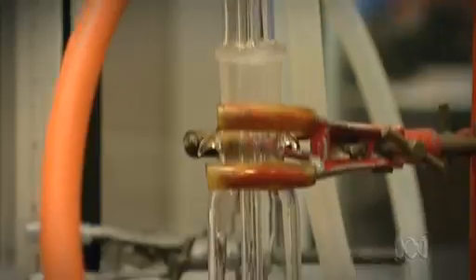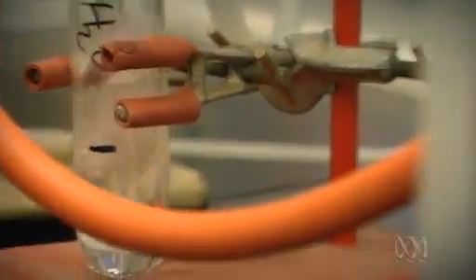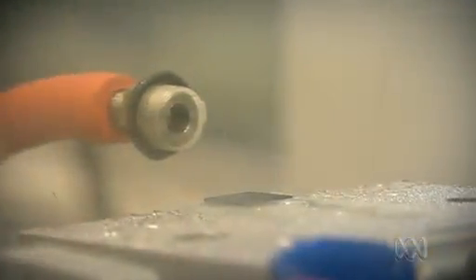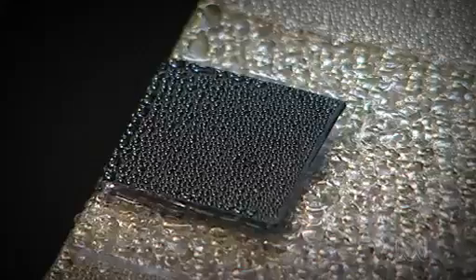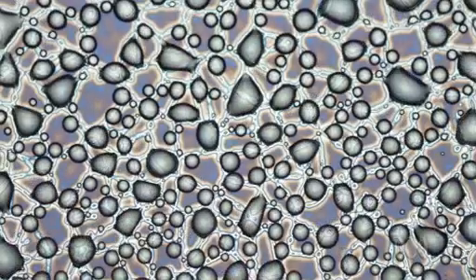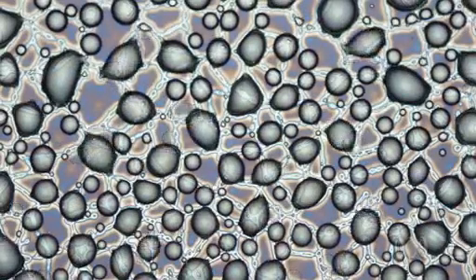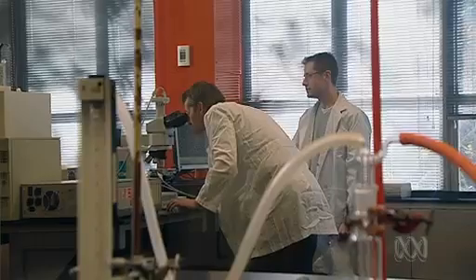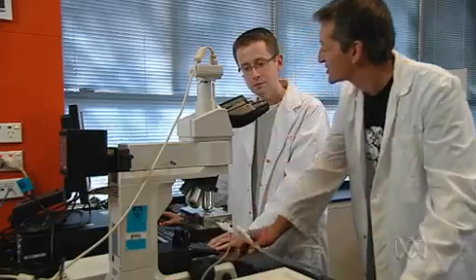Watch what happens when humid air is passed over just a couple of square millimetres of this material. Over 5 minutes, water condenses on the hydrophilic top layer and grows into larger drops. How much does your surface improve condensation? So a test piece like this, you might collect 40 to 50% more water than a corresponding flat film. That's a really impressive increase.